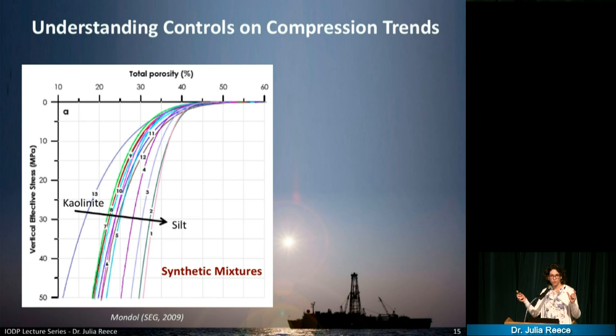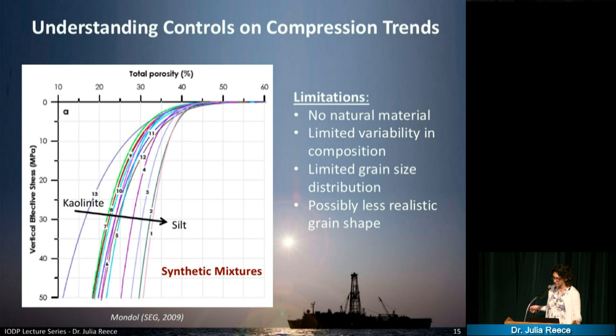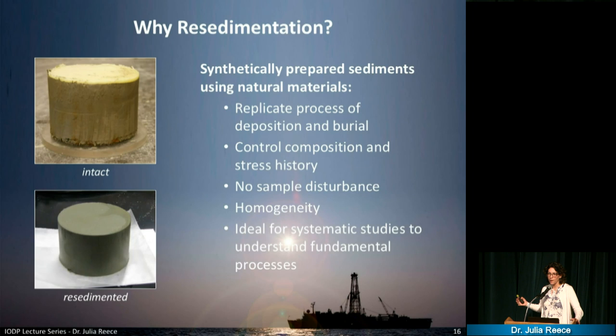I thought, well, wouldn't it be better if you could use some natural materials and test the compression behavior of those? And so instead of using just two components here and being limited by the grain size and using less realistic grain shapes, I started using a technique called resedimentation, which is a way to simulate the sedimentation and the burial that's happening in nature, but you do it in the lab under controlled conditions. You can really decide what you want to put in there and make your own sediments, make your own muds in the lab. So you see an intact sample that was cored, and then its resedimented version down below.